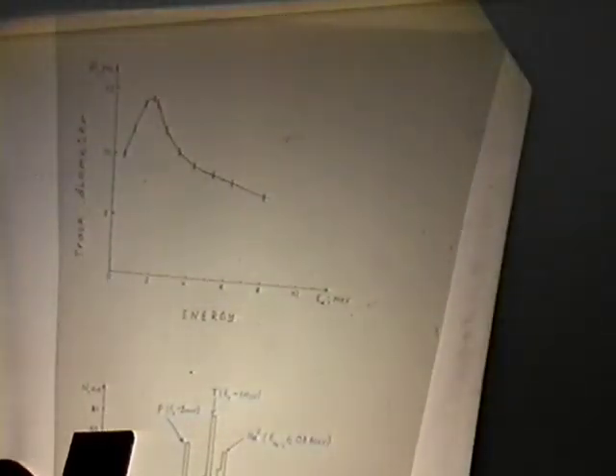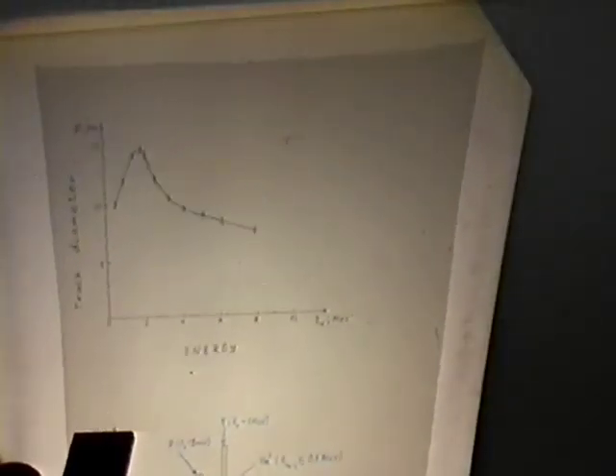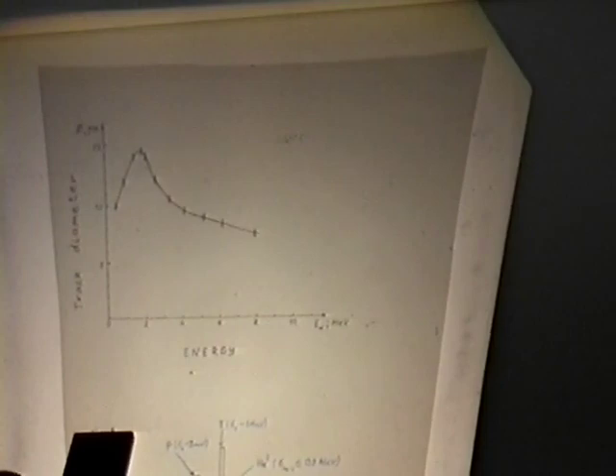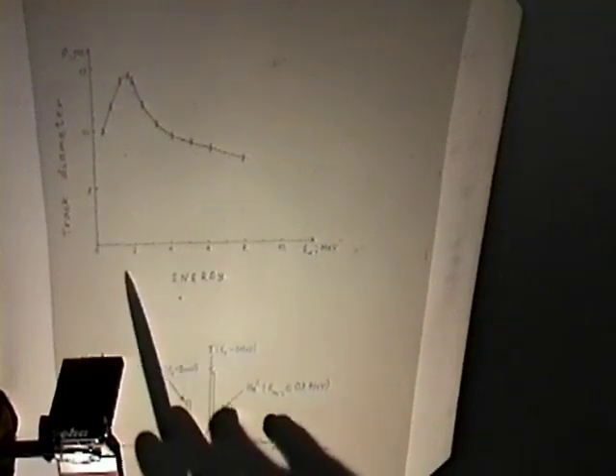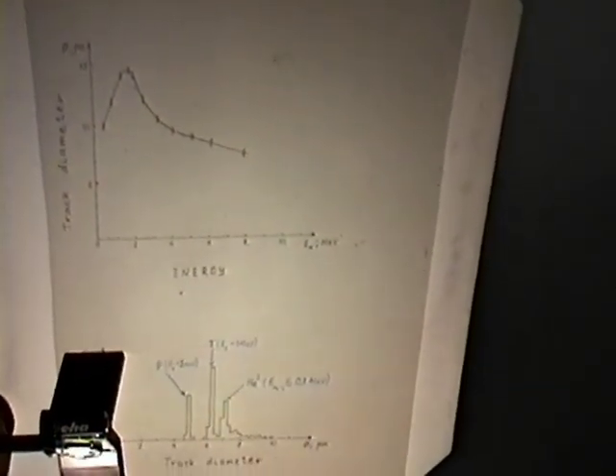To investigate the CR39 response to helium-4 nuclei, the detector was irradiated by alpha particles from plutonium-239 and radium-226 sources through different aluminum foils. You can see the distribution of track diameters versus alpha particle energy for this measurement.